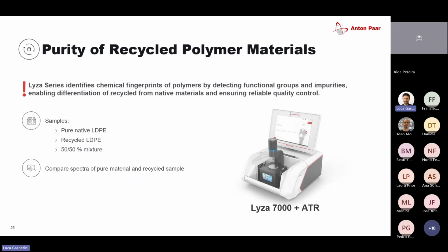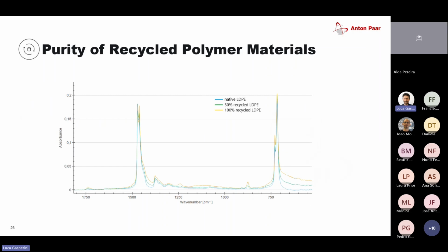So how do the spectra look? The yellow line corresponds with 100% recycled LDPE, the blue line corresponds with only virgin LDPE, and then we have a mixture, as I said, 50-50. And there are some things to point out. For example, here we have a peak which we do not see on the virgin LDPE. When we think about the quantification example, this is typically a calcium carbonate filler peak.